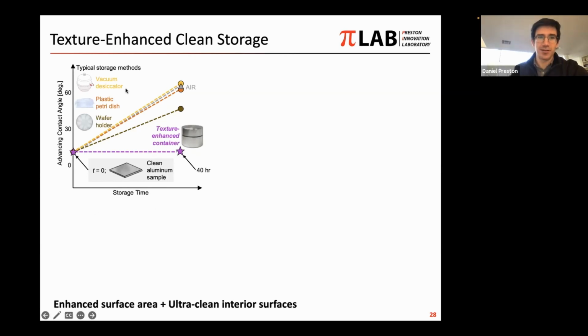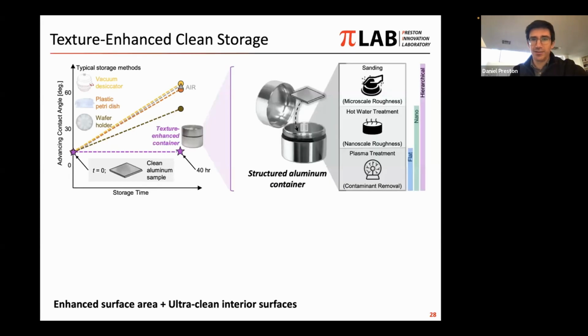We compared this to a couple of other methods, vacuum and different types of wafer holders or Petri dishes, as well as storage in air. These methods were not effective. We still had an increase in the contact angle over time as a proxy for the carbon contamination. But with our approach, over in this case 40 hours, we had no observable increase in the contact angle over time. So this is just the summary. We'll get into some details.